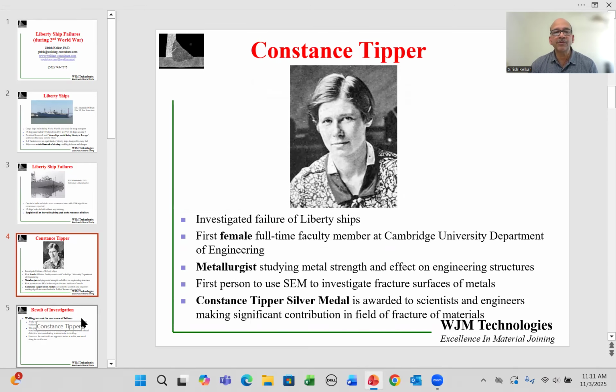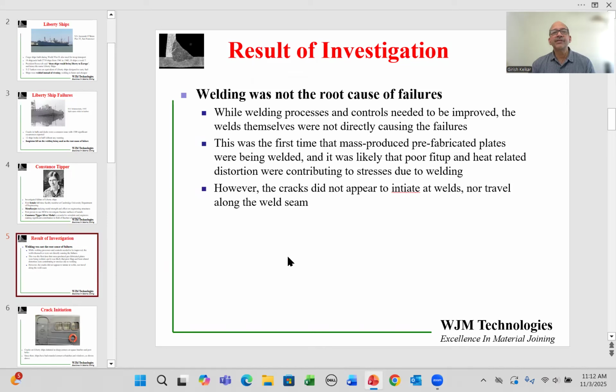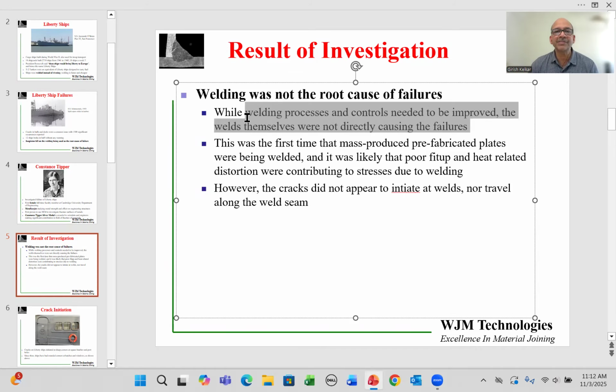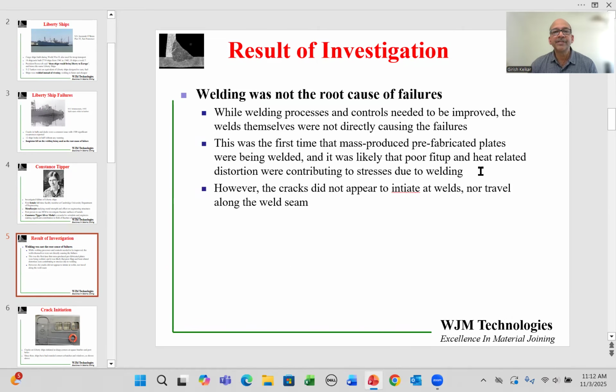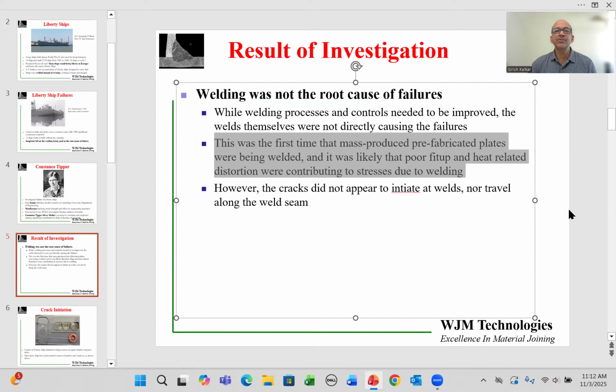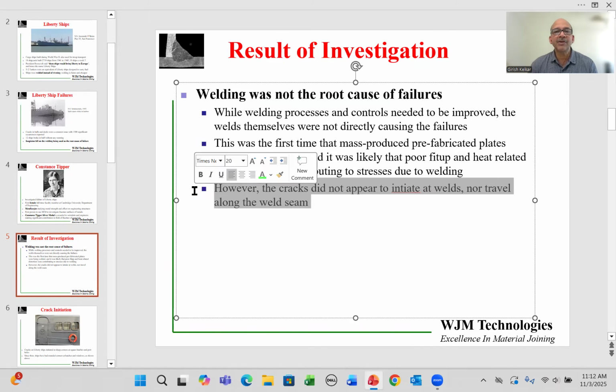So what was her conclusion from this investigation? She concluded that welding was not the root cause of failures. While welding processes and controls needed to be improved, the welds themselves were not causing the failures. This was the first time that mass-produced and prefabricated plates were being welded, and it was likely that poor fit-up and heat-related distortion were contributing to stress due to welding. However, the cracks did not appear to initiate at welds nor travel along the weld seam.